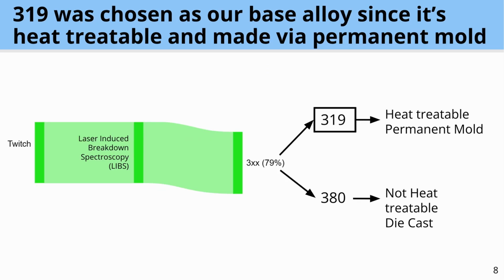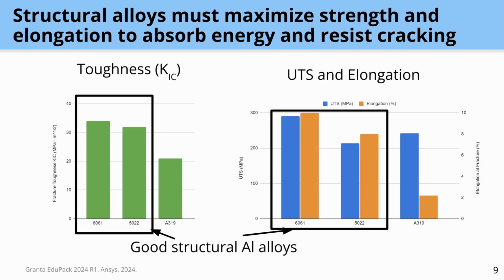So from the 300 series that comes out of Twitch, most of it's either 319 or a 380. And for our base alloy for this project, we chose 319 since it is heat treatable and can be made via a permanent mold, which is what we have at our Michigan Tech facilities. In order to maximize this 319, we have to find a way to maximize its toughness values, its ultimate tensile strength values, and its elongation values, which will make it a good structural alloy.